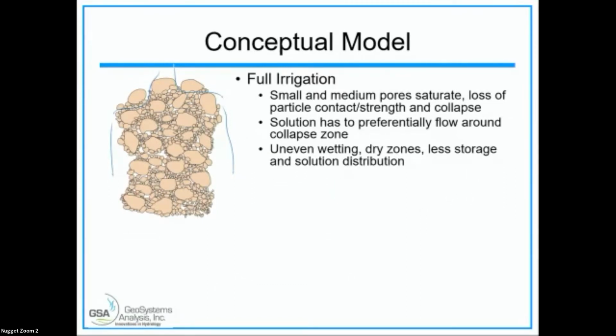You're getting the small and the medium pores saturated. You get loss of the particle. If the agglomerate is not holding together, you could get movement, and you lose your soil strength, and the thing just collapses. And so what happens is what we saw in the dye test. The solution goes down and then has to go around. So you get uneven wetting, dry zones, less storage, and poor solution distribution.